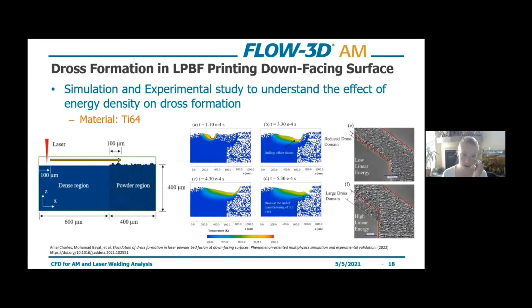So researchers at DTU did a full-scale study where they looked at dross formation in printing on overhangs. So a different scenario from the previous case in that in this case, they're actually operating in keyhole mode. So once they hit the edge of that dense region and get into the powder region, well, for one, the thermal conductivity in the powder region is a lot lower because there's less contact between individual powder particles. And so the conduction, the ability of the material to conduct the heat away is also lessened. And you get a lot more heat retention locally once you hit the powdered side of the domain.